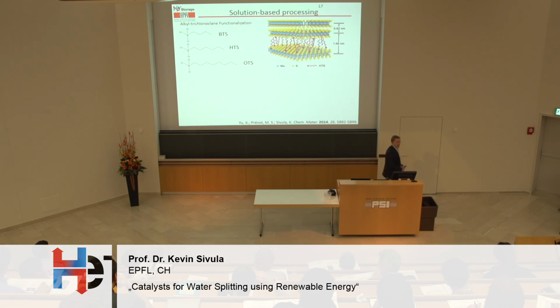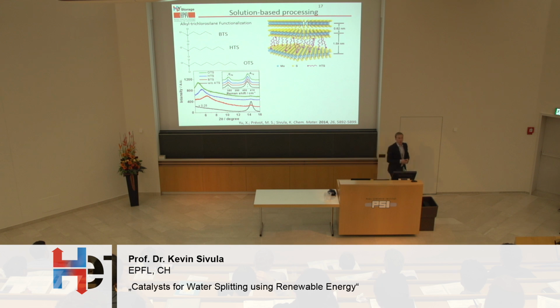Now, very recently, our group found a special type of surfactant here, this alkyl trichlorosilane group, which can, in certain cases, depending on the treatment, attach to the surface of these transition metal dichalcogenides, in this case molybdenum sulfide, and really prevent the restacking of these sheets. And that can be clearly seen when we look at the XRD, which of course measures the distance between the planes using X-ray diffraction.